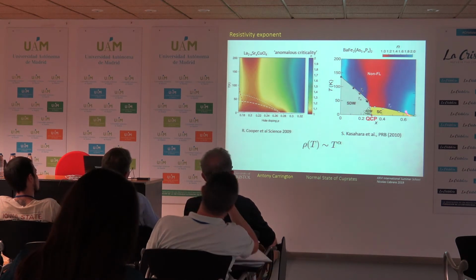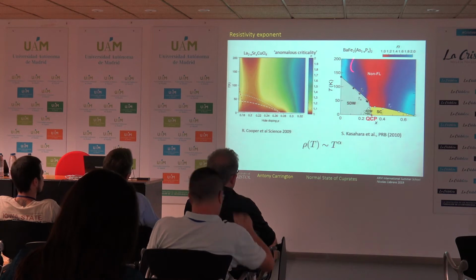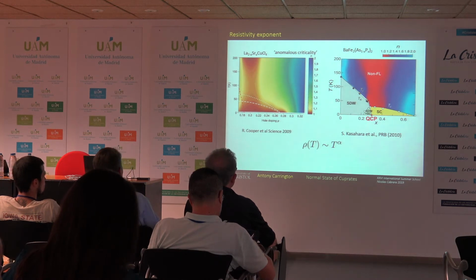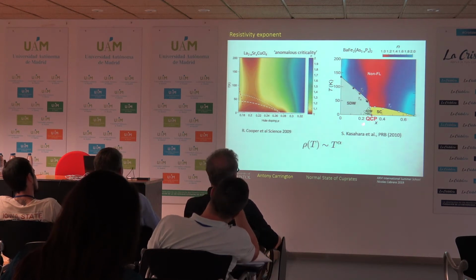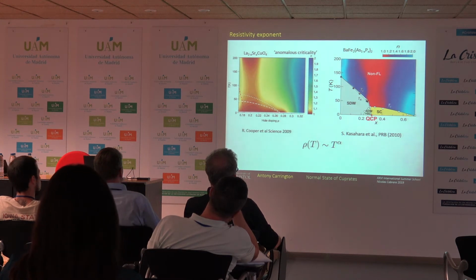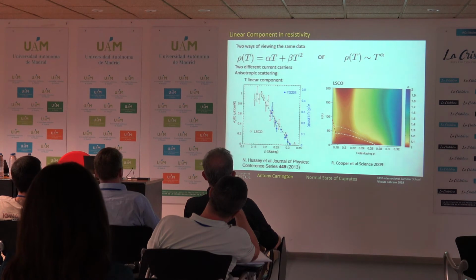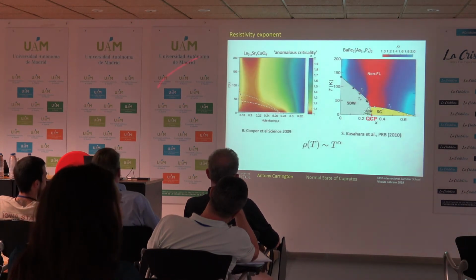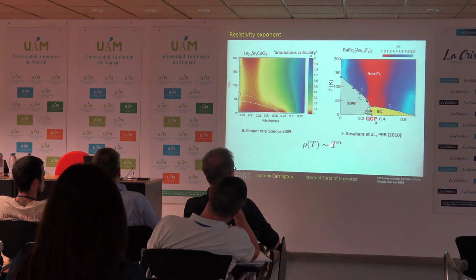Okay, and that contrasts a little bit with the iron-based superconductors. So this is data from Shigeru Kasahara and Yuji Matsuda's group, where they showed that there is indeed this fan of linear resistivity which stems out from the quantum critical point in this material. So this is a popular way of representing the data by looking at this exponent where rho is T to the alpha.